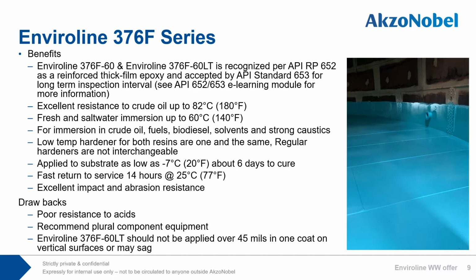Can be applied to a substrate as low as -7 C. Takes about 6 days to cure. I witnessed this on the North Slope, Alaska, in the winter several years ago, where the outside temperatures were a calm -45 to -50 C. Fast return to service in 14 hours at 25 C.